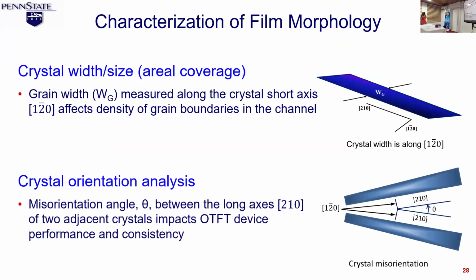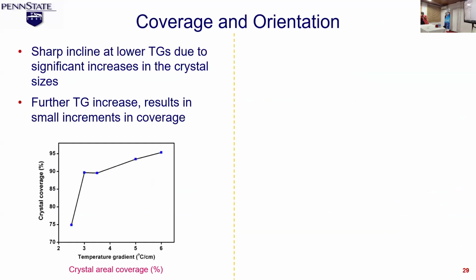So after obviously attaining the type of crystals that we want, what I did was then to actually characterize it. So what kind of area coverage would I get? What kind of orientations am I getting from the substrates? For the area coverage, it was just doing a line scan over the substrate and essentially comparing the area that was covered with crystals to the entire substrate. And for the crystal orientation, again, line scans, but pretty much counting the number of misorientations that we have from the crystals.